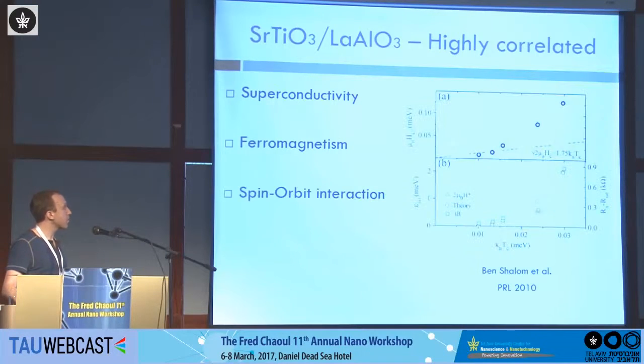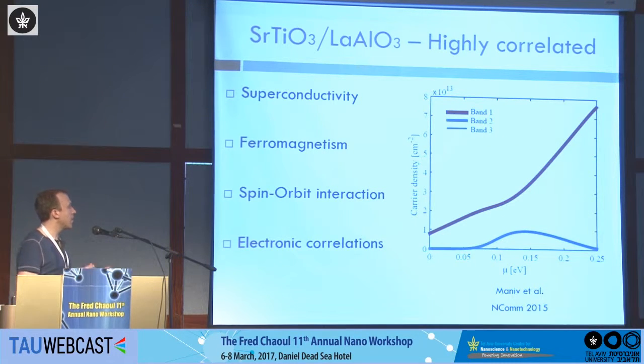a while ago. Moreover, it has spin-orbit interaction. It means that the spin has interaction with the orbital momentum of the electron. This is a measurement from our lab, Moshe Ben Shalom. And also it has Coulomb repulsion interactions between different bands that actually change the band structure itself. So it's really interesting, and it has a variety of phenomena that show it's highly correlated.